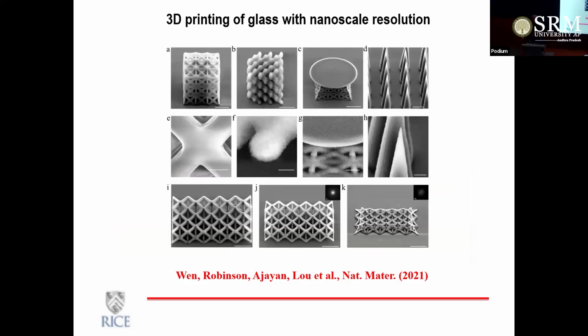And in recent times, in the last 5 years or so, there have been lots of developments in this two-photon polymerization approach of creating 3D printed structures. You basically take a polymer precursor and polymerize it using lasers, and you can actually get resolutions that are sub-micron. Right, so this is one paper that we published a few years ago on silicon dioxide, and using the right precursors, we were able to print very complex structures similar to the ones that you saw for the carbons, again with about 200 nanometer resolution, which is really very, very good, right? Again, in the last year or so, several papers have come out from different groups suggesting you can make these nanophotonic devices using the same approach. You can create oxides like titanium oxide, which have really amazing properties optically. So, we were very interested in thinking whether you can do carbon materials printed in the same way, right?